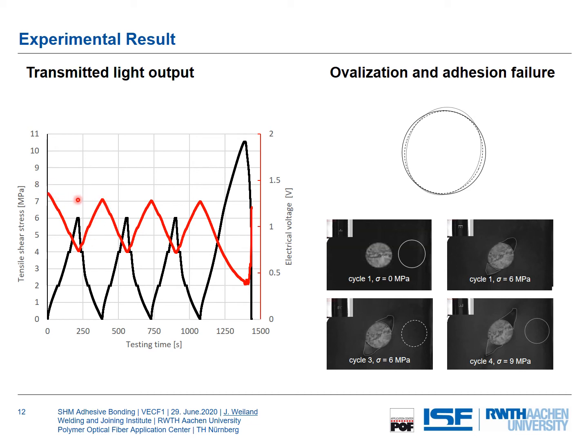We have a little bit of a shift in the maximum light, which we definitely have to investigate. But up to date we are very proud of these results. And then at the end, when we test until failure, you can really see the light transmission going down, down, down, until the adhesive layer fails, and then, as you can see here, it's not very smooth. You can clearly see that something happened in the adhesive bond. So we are able to really get information about the stress state of the adhesive layer when we only look at the red line, the sensor signal. So that was the one thing.